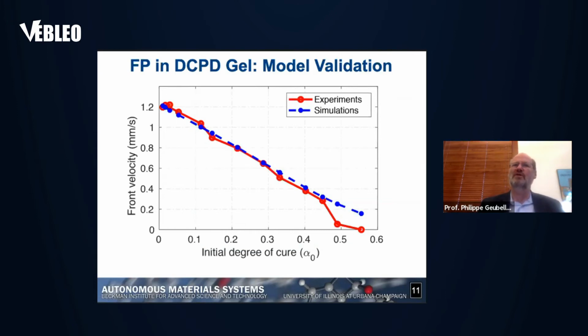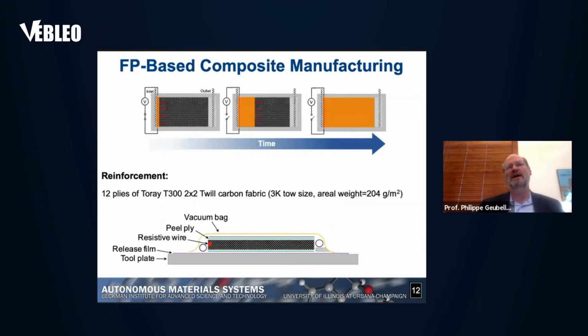So the key contribution of our work has been to apply this to the manufacturing of thermoset composites. And this is an illustration of how we achieve this. We start from a carbon fabric, in this case a 12-ply Toray T300 carbon fabric. And we start with the traditional process of vacuum-assisted resin transfer molding. So we basically infiltrate this fabric with the monomer, which is relatively straightforward because this monomer is not viscous. It has the same viscosity as water.